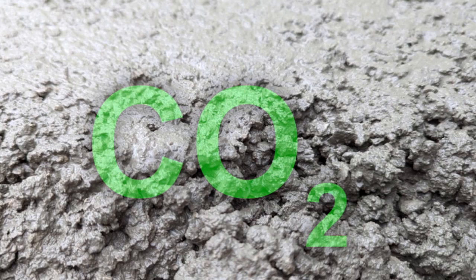In contrast, the new carbon dioxide sequestration pathways discovered by the authors rely on the very early formation of carbonates during concrete mixing and pouring before the material sets, which might largely eliminate the detrimental effects of carbon dioxide uptake after the material cures. The key to the new process is the addition of one simple, inexpensive ingredient, sodium bicarbonate, otherwise known as baking soda.